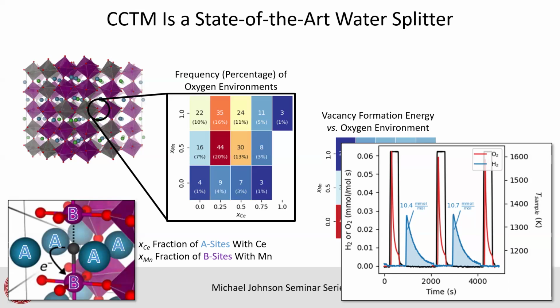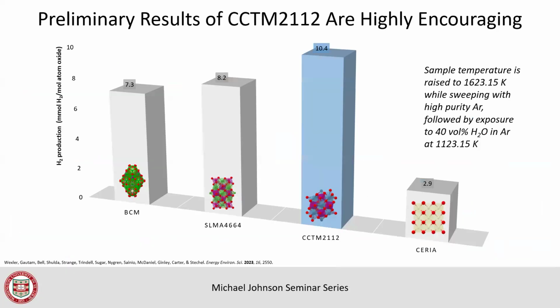Then in the next part of the cycle, the red kind of tails off, and we see a new thing emerge. What happens in between the red and the blue is that we cooled it off, we presented it with water, and we saw a new peak. That new peak was related to hydrogen. So you can compute the area under that curve, and that tells you how much hydrogen you were able to make by producing these missing atoms and replenishing them by splitting water. And we were able to make a certain amount that, if you compare it to the other materials that are used for this process, is better than all of them.